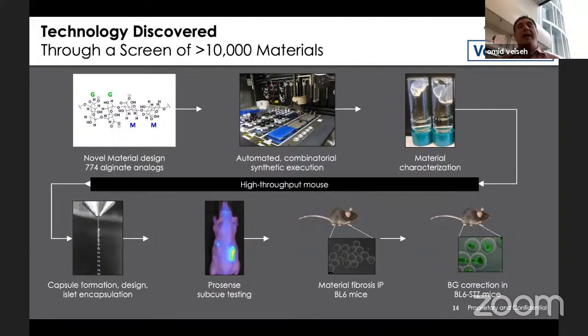And we thought maybe we can apply the same exact approach to the discovery of novel biomaterials, which could alleviate foreign body response recognition and have better outcomes in terms of fibrosis. So we generated a library of alginates, which were chemically modified. And this was a very broad screen. And at the time, we didn't have any biases about which molecules could work. We tried to go as broad as possible.